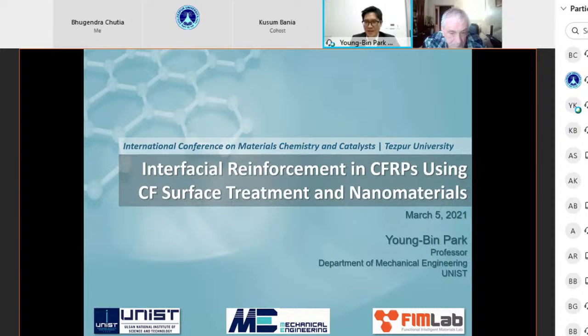In part two, this has to do with both processing and also interfacial strengthening. So in this case, we take polyamide 6,6 as the matrix material and carbon fibers as the reinforcing material. And at the interface, which is formed between the carbon fiber and the matrix, we include graphene oxide and carbon nanotube in a hybrid form, and we do so by using a process called in situ interfacial polymerization.